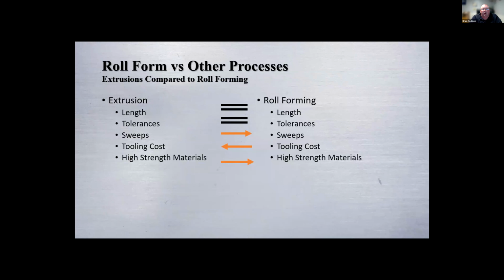Tooling cost, as you all know, if you do aluminum extrusions, tooling is usually very inexpensive on an extrusion compared to roll tooling. But when you get to high strength materials, they call it aluminum extrusion for a reason, because that's pretty much the only material that can go through it. Otherwise, the metal that you're pushing through it is the same as the metal that it's going through, and it will destroy the dies. So when you're looking at those processes, that's one of the key things about roll forming: the ability to run different types of material, not just aluminum.